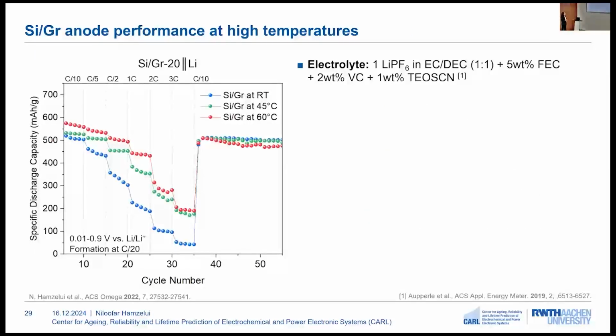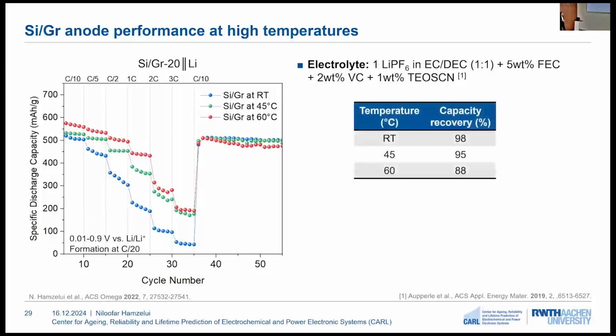Then the electrochemical performance of the anodes was measured at high temperatures. For this measurement, an electrolyte with a high temperature enabler additive of TeOSCN was used, which was previously investigated in our group by Felix Aupperle. And here we can see the rate capability of the cells at room temperature, 45 and 60 degrees.